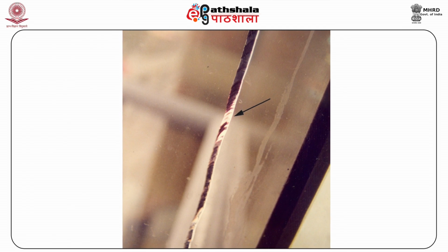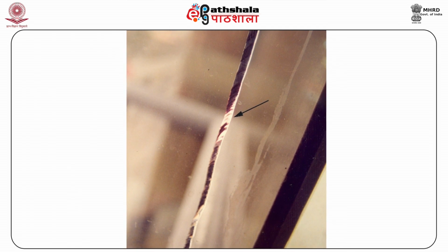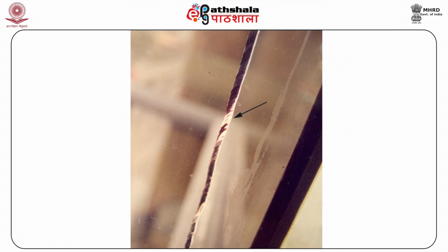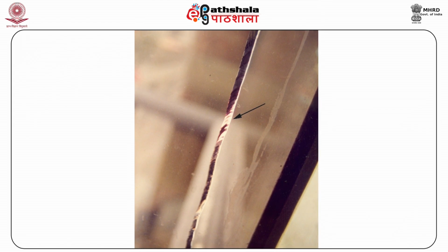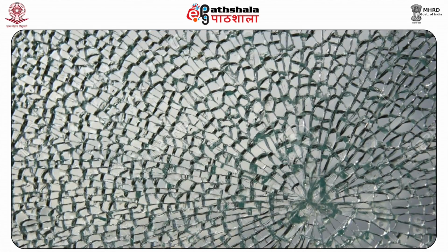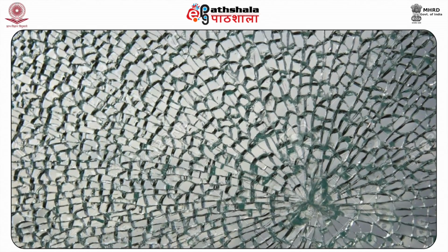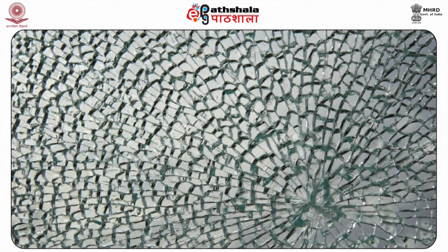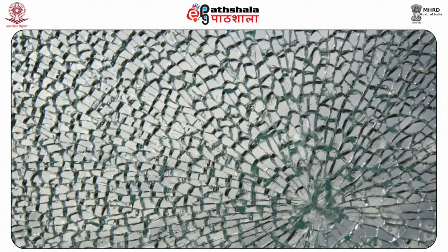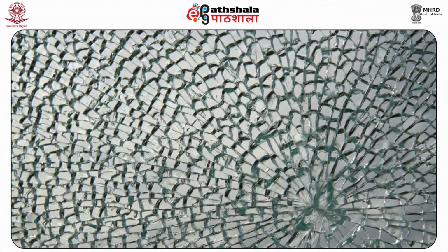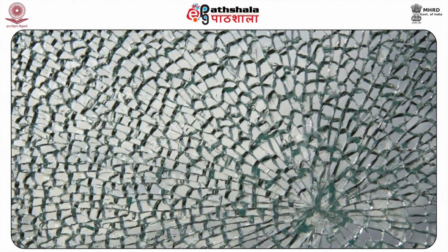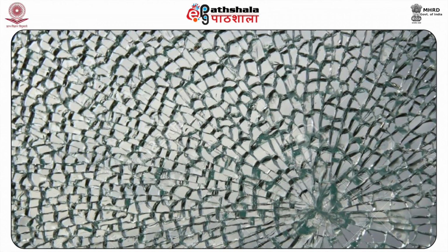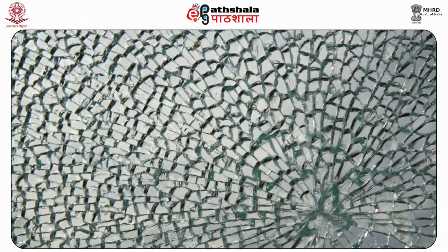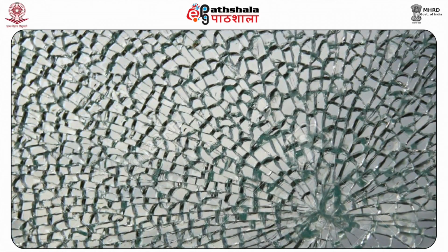Observe only the Wallner lines on the radial cracks nearest the point of impact. If the impact site is not preserved, the glass must be reconstructed. The original orientation of the glass must be known to complete the determination.